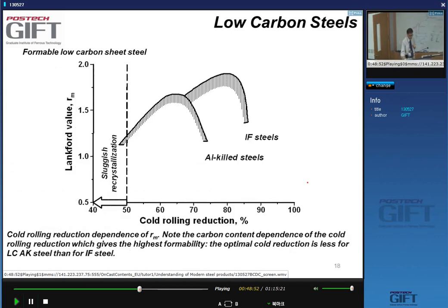Okay. Now, let's have a look at the impact of the amount of reduction, again, that we give to steels before batch annealing. So if we look at the low-carbon aluminum-killed steels, yes, we see that the window in which we do the reduction is 50 to 70 or slightly less than 70%.